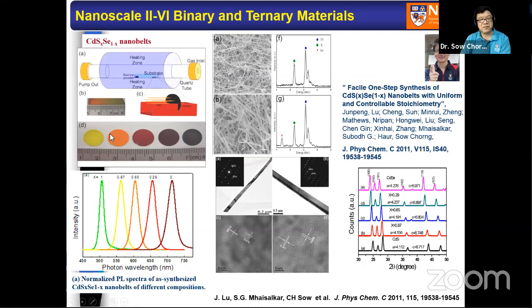This is a very interesting system. If you have pure CdS, it looks yellowish in color. Pure CdSe looks more dark brown. And if you can tune the relative compositions of sulfur and selenium, CdS_xSe_1-x, x being from 0 to 1, you can have different percentages of sulfur and selenium. And the beautiful thing is that cadmium sulfide has a band gap, cadmium selenide has a different band gap, and anything in between has a tunable and engineerable band gap. So that's why the photoluminescence shows up very nicely in this particular manner. It has different colors as well.